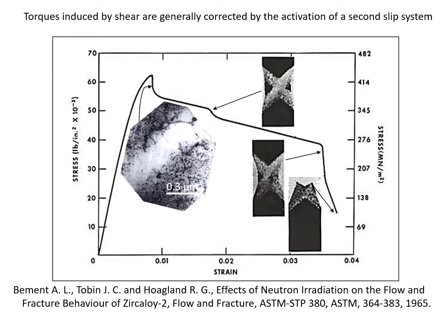That's graphically illustrated when it comes to the stress strain curve. And here's a stress strain curve for a Zircaloy-2, which is actually being irradiated. What this illustrates is the operation of what are called dislocation channels. I haven't talked about that, but I think I might at some point. Dislocation channels involve the gliding of dislocations through volumes of the crystal and the interaction of these dislocations with hardening centers. Now, it has to be a dislocation loop.